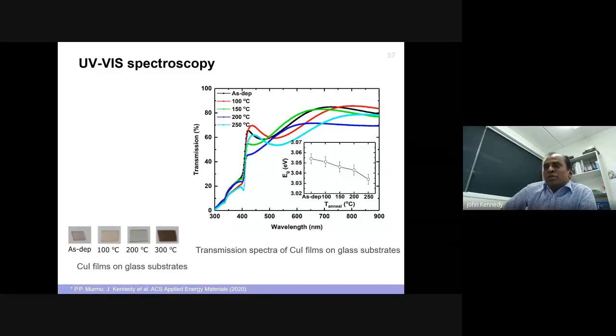When you anneal too much, these nanoparticles become larger, and you get more agglomeration. The surface area is no longer the same, and you start to get more voids. So it's quite good up to 100 degrees, maximum 100 degrees, I would say. But the beauty is the transmission still stays, because you have to maintain transmission as well. Otherwise, your visible light cannot go through, right? So you need to find the balance there. Yes, the band gap does change when you anneal for a long duration of time.